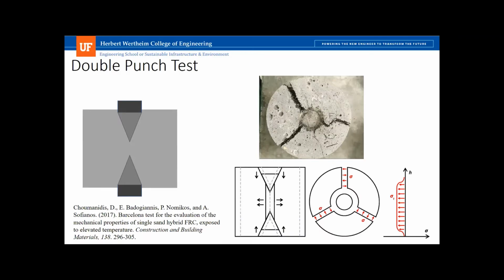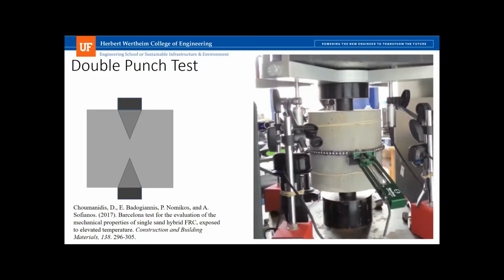And when you look at diagrams where you try to calculate the stresses, you can get an equation that allows you to calculate the tensile stress based on the load applied to the punches. Traditionally, the displacement part has been measured using the change in circumference of the sample using an extensometer. It works really well. They have good use and history of use of this in Spain.